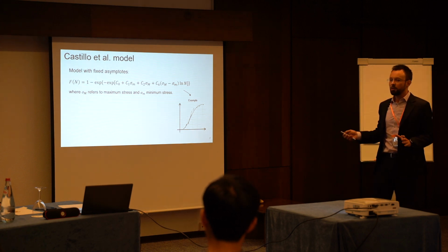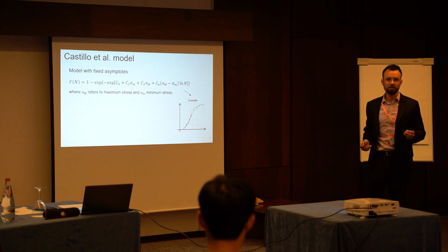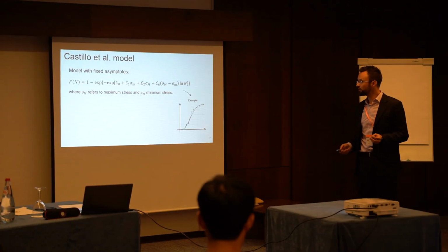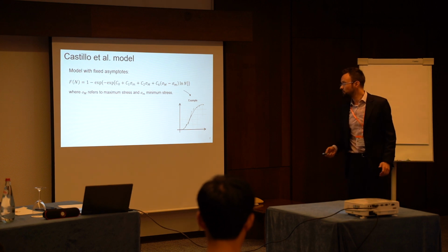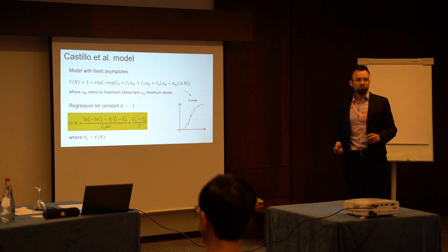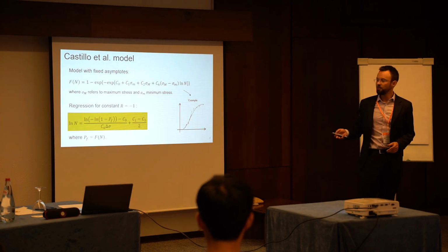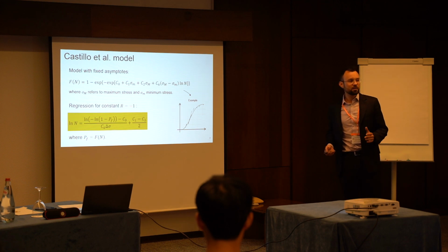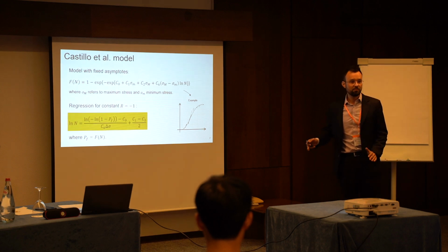I will show the probability of failure, or cumulative density function, of the general model with fixed asymptotes. As we are interested in the regression equation, here you can see it in yellow for constant stress ratio, minimum and maximum stress. It depends on C parameters.